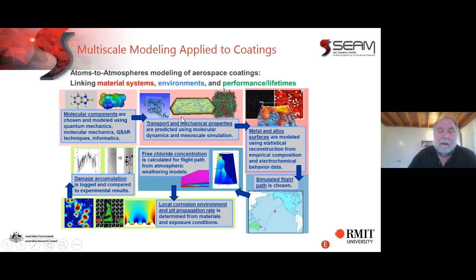They had part transport models to look at how the inhibitor would be transferred through the paint system and to cracks and other defects that occurred that were corrosion sites. They had a model looking at the alloy structure and looking at where those intermetallics, which provide strength but also act to stimulate corrosion, are. So that was the basic material structure.